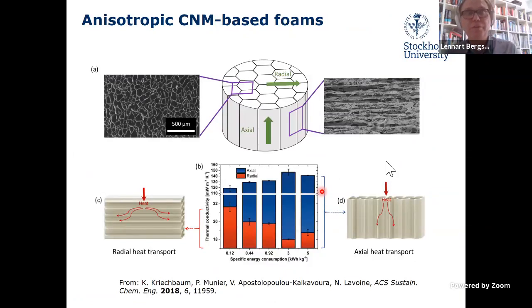And that's something clearly manifested here. You can see the difference in the radial and the axial heat transport, where the red is the radial. The specific energy consumption relates to diameter - the higher energy consumption, the smaller the diameter, and then the radial thermal conductivity is reduced down below the value of 25, which is the typical value for air.